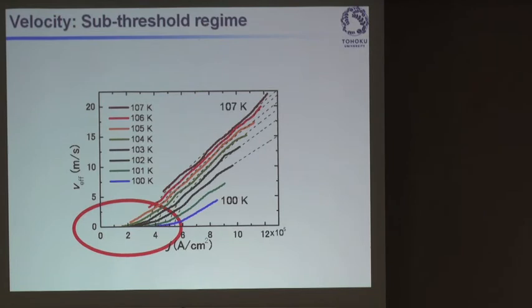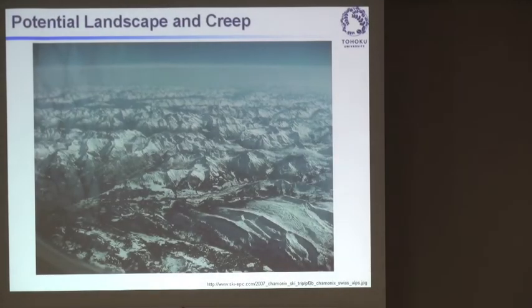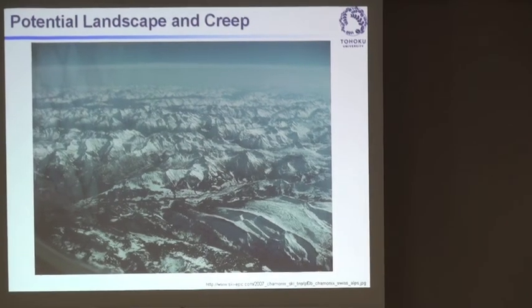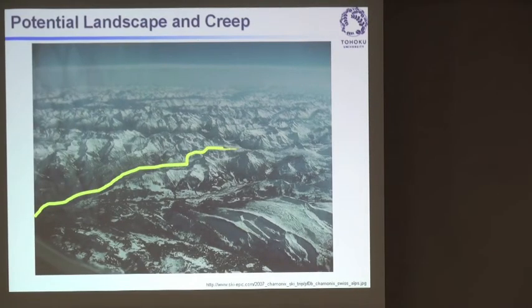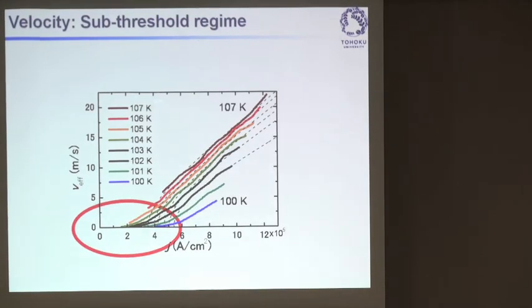Which means that with very small current, we see very slow motion of domain walls. The physics here is very different from the spin transfer physics here, because we have a potential landscape which is dominated by randomness, for example. And we have a domain wall running through this random potential. There will be a collective phenomenon showing up when you try to first move this domain wall. That's physics that is completely different from the physics shown up here.